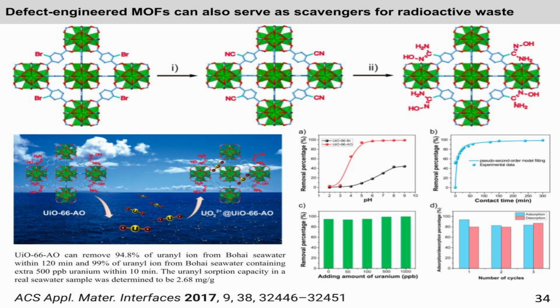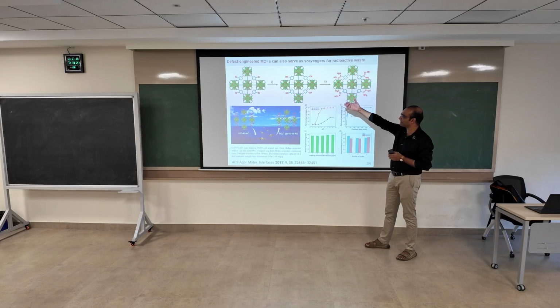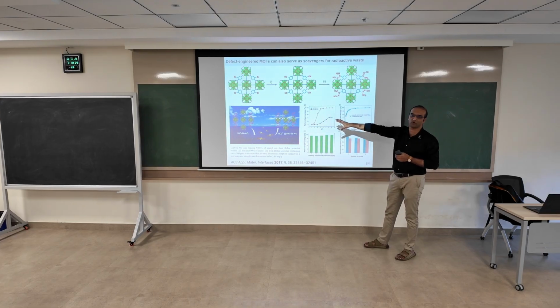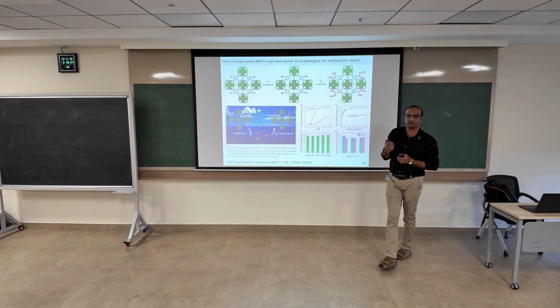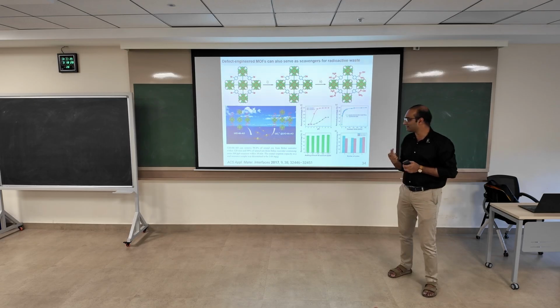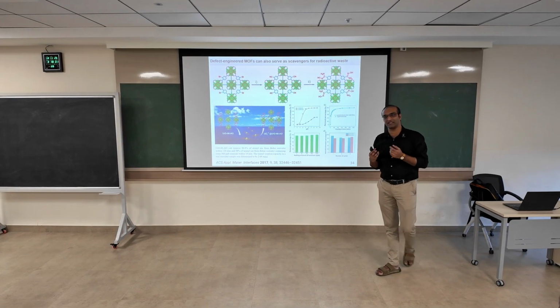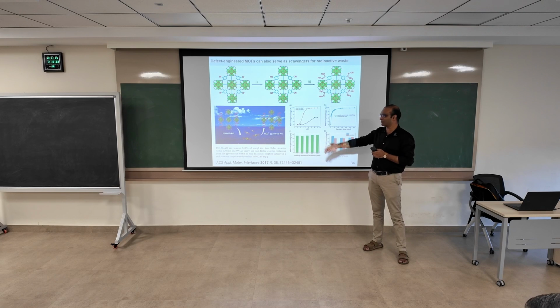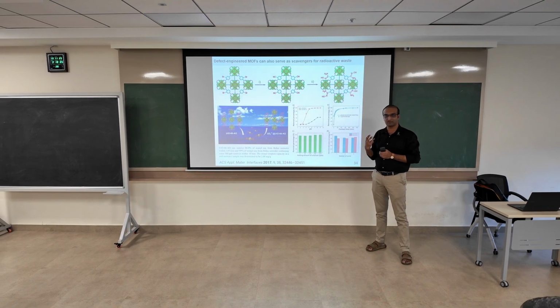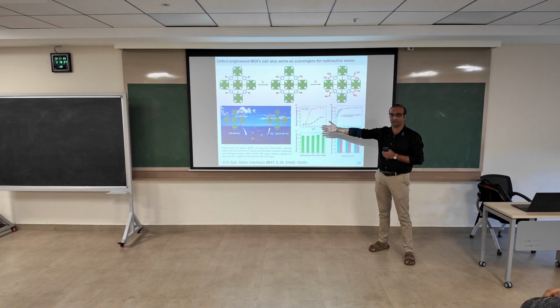And then this is another example. This is another MOF where you can convert the linkage. This is called post modification. After you make the MOF, you can change this particular linkage, or you can add on to it. They made amidoxime. They started with cyanide, and then they got this amidoxime MOF, and this is very selective for uranyl capture from seawater. See, in seawater there is not much. There's a very small concentration of it. But if you could selectively get all of it, a lot of that uranium can be used.